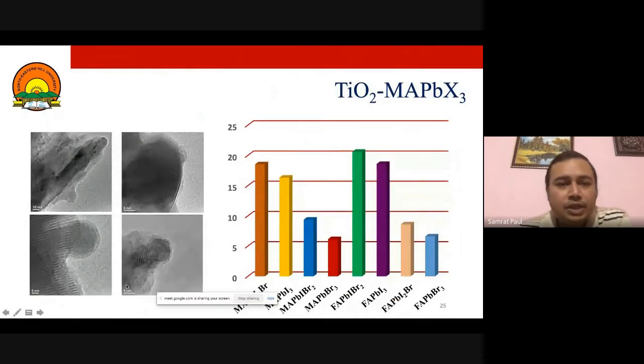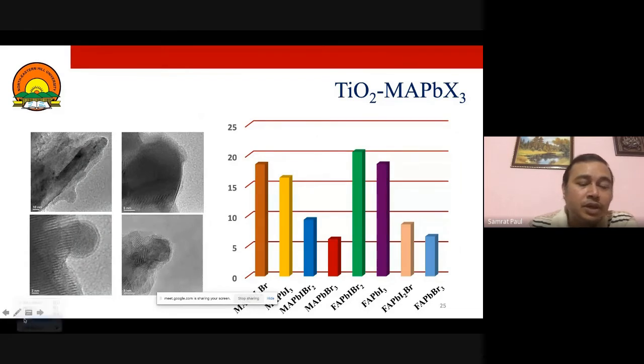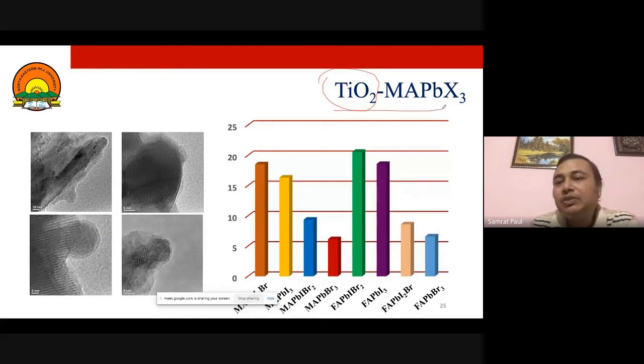So again, I'll not go to various results directly. I'm coming to whatever work we did. Again, these organic perovskites are being covered with TiO2, which is also mixed phase TiO2. So this type of active material we have made. TiO2 is slightly UV active, and these are visible active. So the mixed phase TiO2 shows a band gap of around 3 electron volt because it has got more of rutile than anatase in it. And methylamine perovskites have band gap in the range of 1.8 to 2.2.